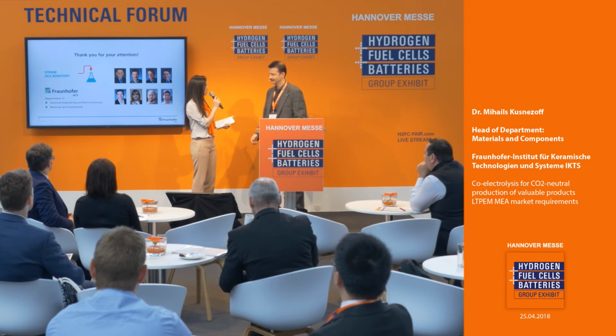All right, well, while people are thinking, you mentioned during your presentation that you expect about a 0.5% degradation of your stack over, was it 1,000 or 10,000 hours? 1,000. For 1,000 hours. Would you expect that to continue to be a linear degradation, or would you expect to see a sharper drop-off once the fuel cell gets a little bit older, has more hours on it? Yeah, it's a linear degradation.